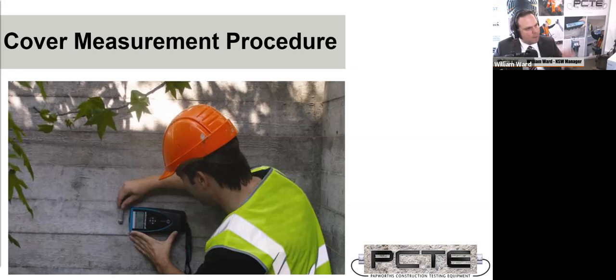That's a compact palm antenna style for curved surfaces. And if I had a really rough surface, like an exposed aggregate, you could lay something like a plastic core flute or a non-conductive material over the top. You won't get quite as good signal with the GPR. It wouldn't really affect your cover meter measurements at all, just to give those wheels a flat surface to turn on. It's actually anything which has a wheel uses that wheel as an encoder to see how far it's traveled. So you've got to keep those wheels turning smooth, and then you can measure with either system.